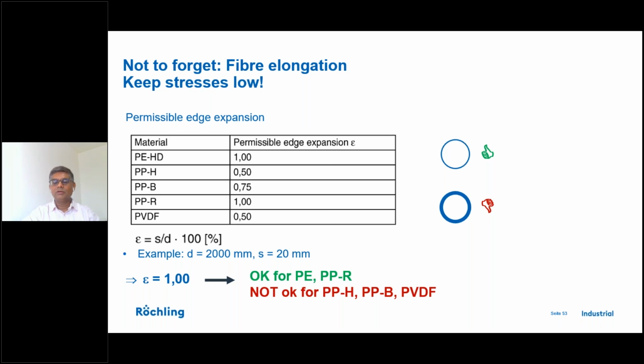Okay. Let me go slightly deeper. See what happens when you have a sheet, and you are trying to bend a sheet and make a circle, you need to follow certain properties. When you are bending it, the outside surface of the sheet will have a V-notch creation, if the sheet is stiff, like polypropylene sheets, homopolymer sheets especially. This has one of the highest tensile strengths. But if you try to bend it, then there will be a V-notch creation.